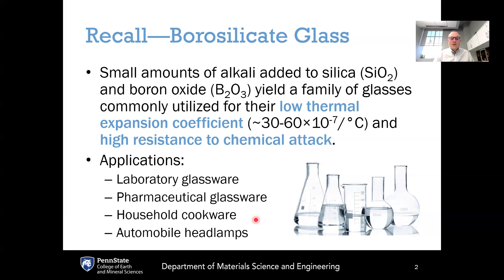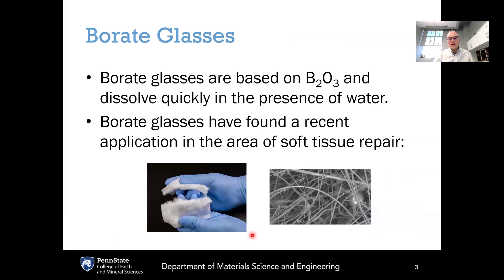Borosilicates are also used for glass baking dishes and household cookware. Please be careful because sometimes sodalime silicate gets sold as glass cookware, marketed under a brand name that would correspond to borosilicate glassware. The older cookware is borosilicate, but as a cost-saving measure, some companies have switched to sodalime, which does not provide the same level of thermal shock resistance. Borosilicate glasses can also be used for automobile headlamps, which are exposed to large temperature differentials.